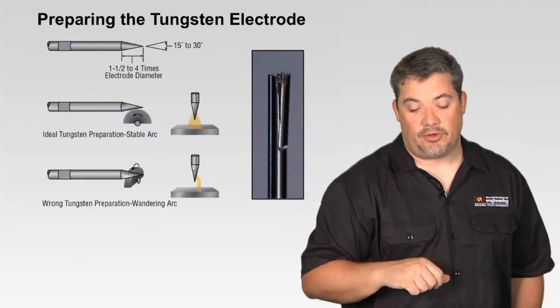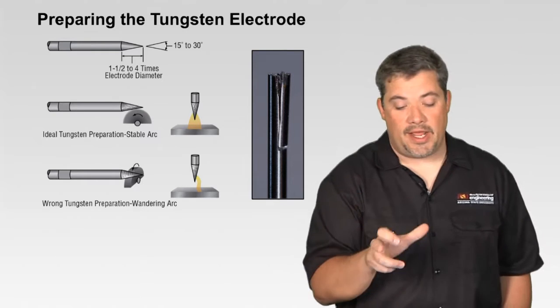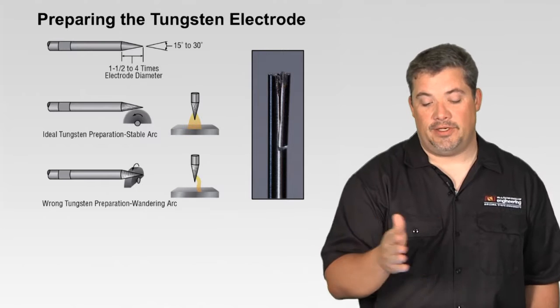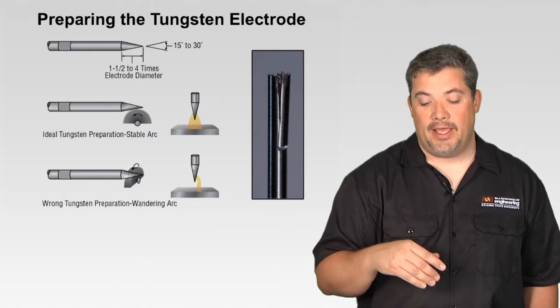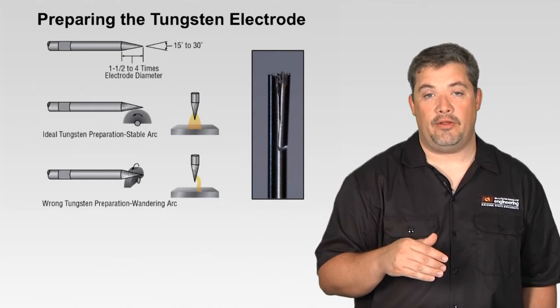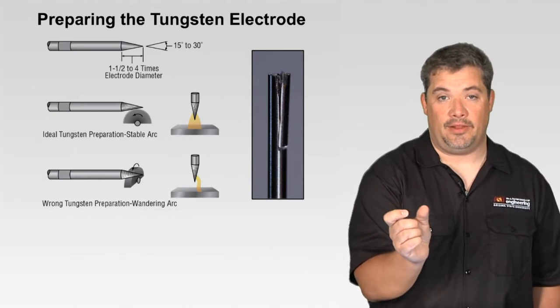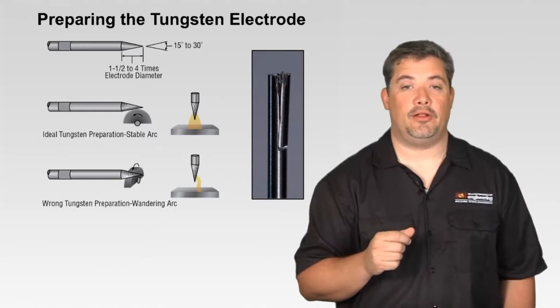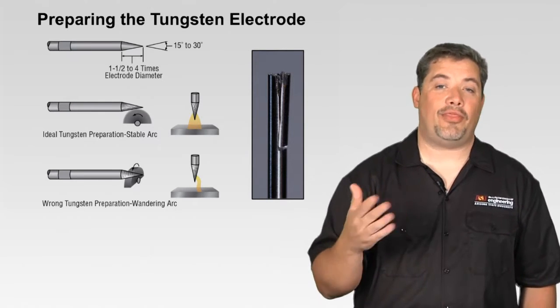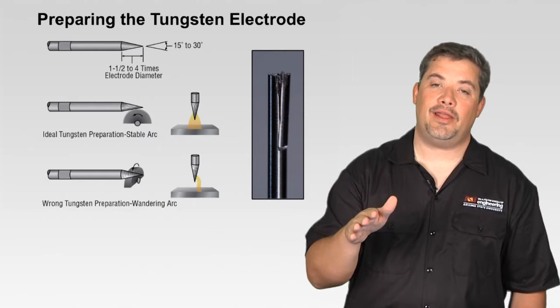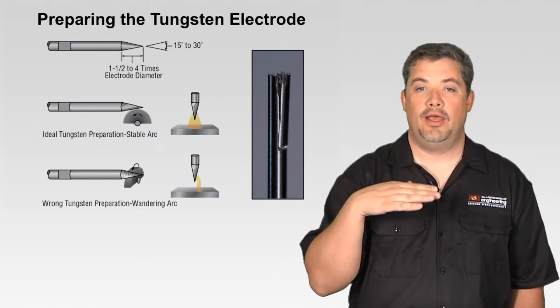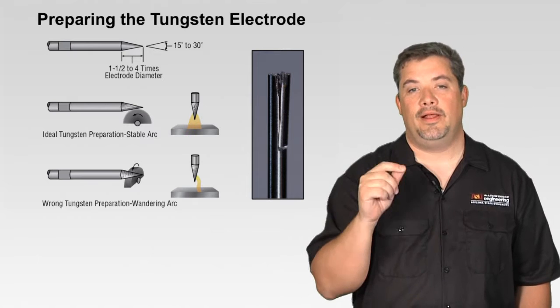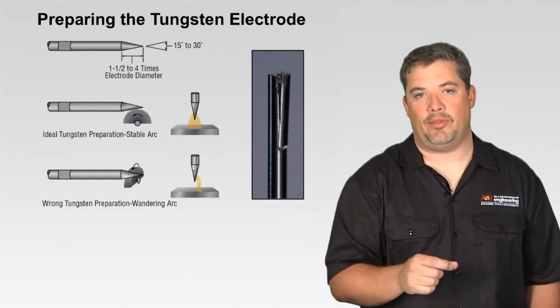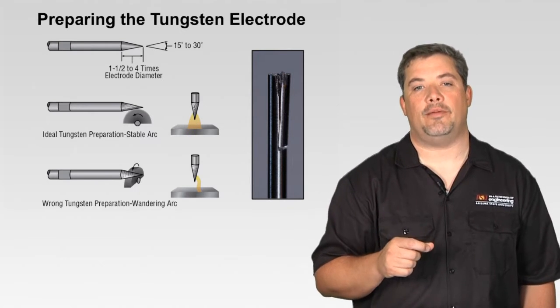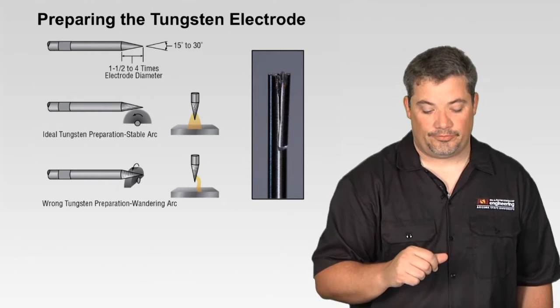So in these illustrations you can see that depth, 1.5 times the electrode diameter going back, is actually a 30-degree included angle. 4 times that length going back is a 15-degree included angle. So I like a 30-degree included angle for everything I TIG weld, so I highly recommend that. An easy way to eyeball it is that that depth is about 1.5 times the diameter.